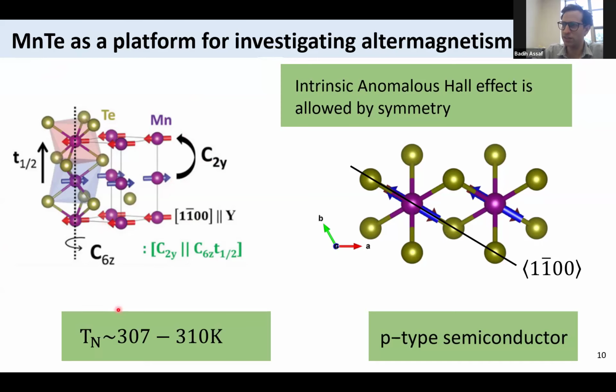Now, what's also interesting is that its Néel temperature is very close, but slightly higher to room temperature. So you can actually tune in and out of the antiferromagnetic state without needing to heat up too much. And this material turns out to be a p-type semiconductor. So a lot of the electrical manipulations that we've learned from the field of magnetic semiconductors over the last couple of decades, as well as topological phases of matter, apply here. You can dope this material, potentially, you can gate it, even though that hasn't been done yet.